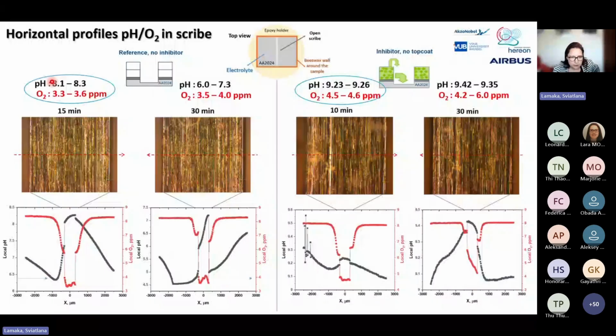Now, these are the results for a reference sample and an inhibitor-containing sample between 20 minutes and 8 hours. And okay, the absolute values, there is still some activity in the case of both samples, but what was really important for us was to understand that we are dealing with a highly electrochemically heterogeneous surface. You see here these outbreaks of local activity, both in the inhibited sample and also in the reference sample.